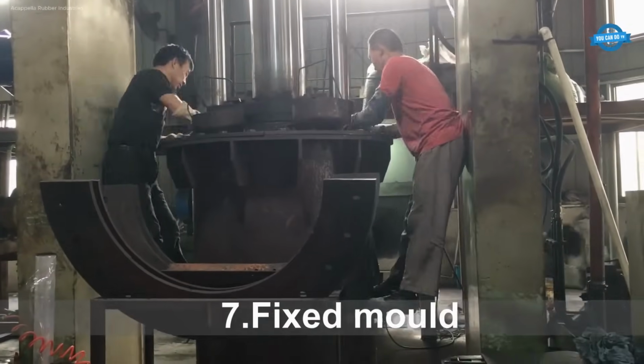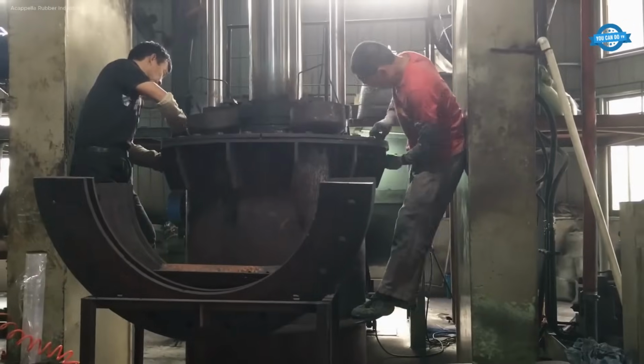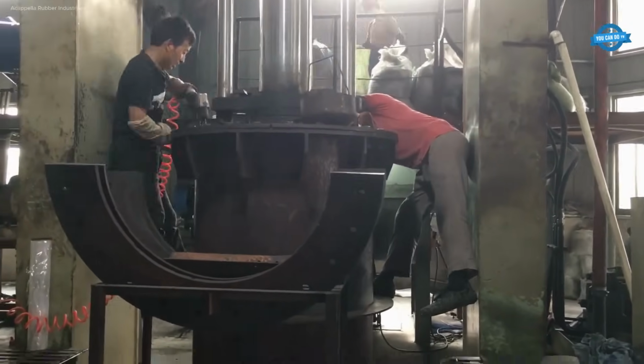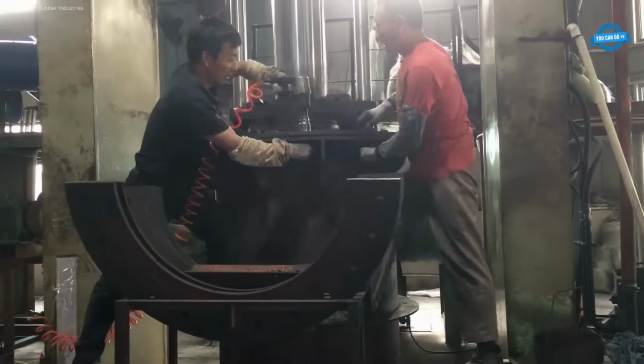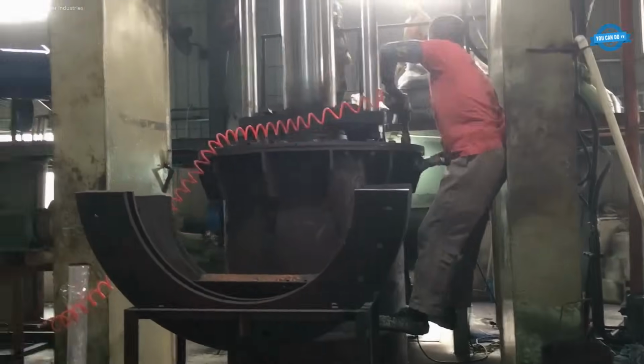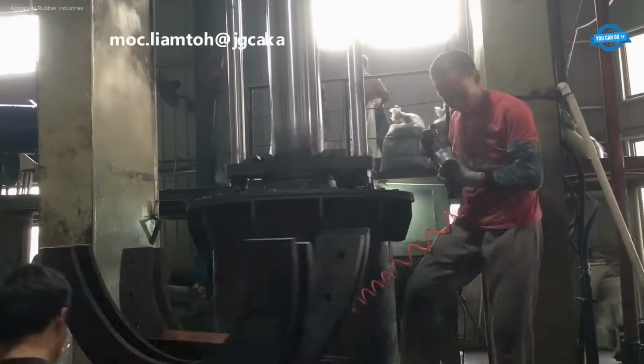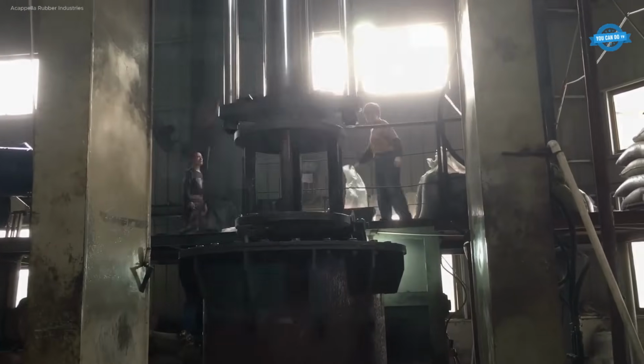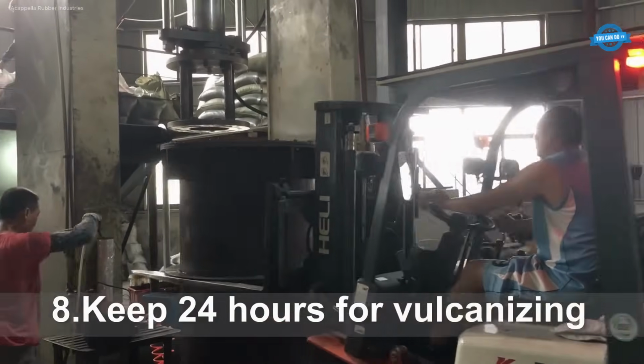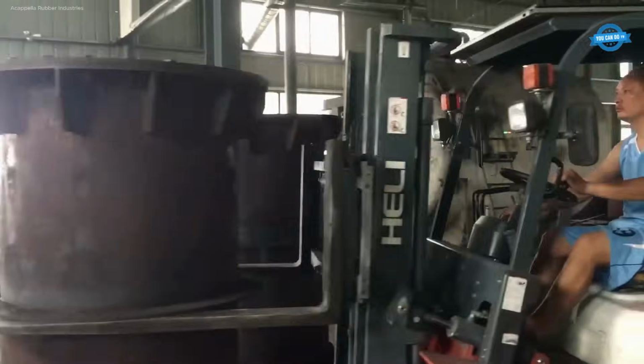After mixing, the crumb binder mixture is manually filled into a large mold. Within 15 minutes, the mold is completely filled. The material is then subjected to hydraulic pressing, which applies high pressure to compress the mixture firmly. Once the pressing is complete, the mold is fixed in place and left to cure for 24 hours, allowing the rubber to vulcanize and solidify into a dense column.